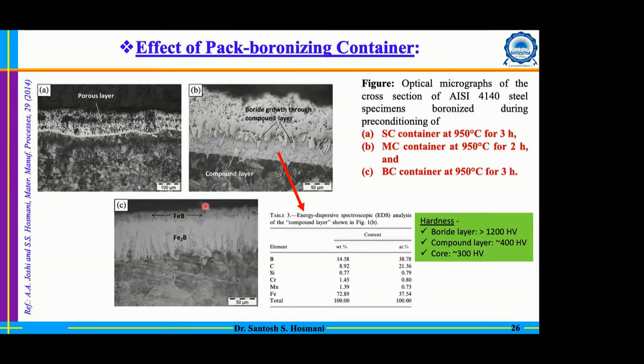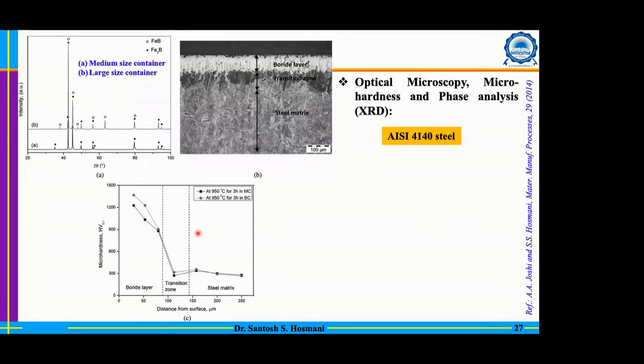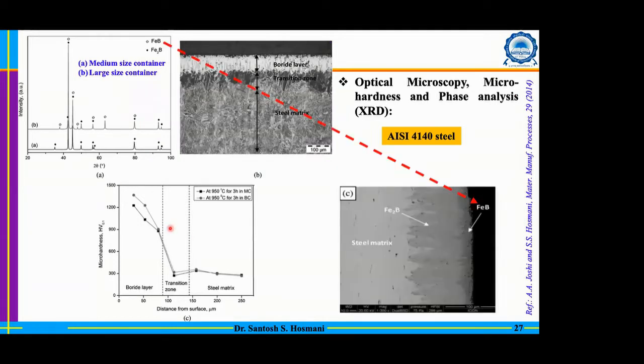And as you keep on increasing the time, and use a bigger container where the potential is also high, you can get the well-grown FeB layer as well as Fe2B layer. That means your container size and the amount of powder with respect to the surface area of your material component is also very vital in governing the kinetics of your process. Okay, so that is also something we need to understand. And here is another interesting thing. In the case of a medium container, we are not seeing any kind of FeB layer formation.